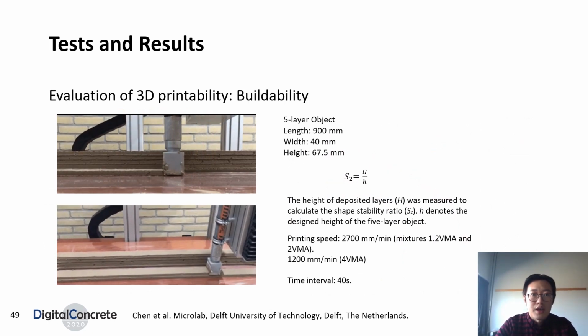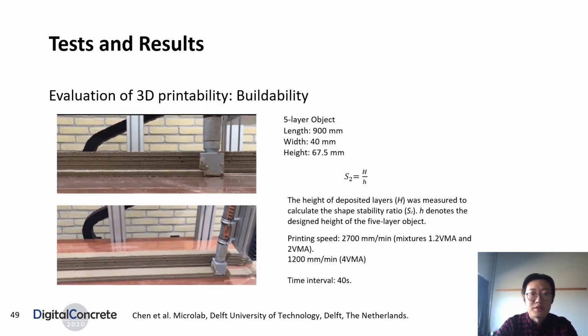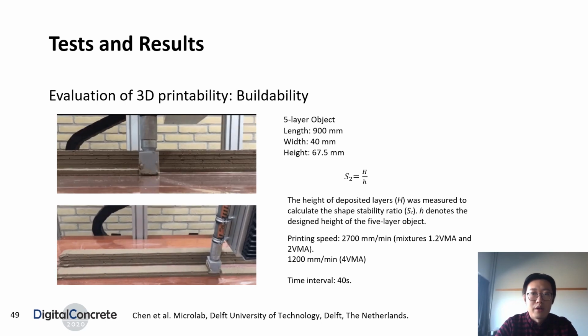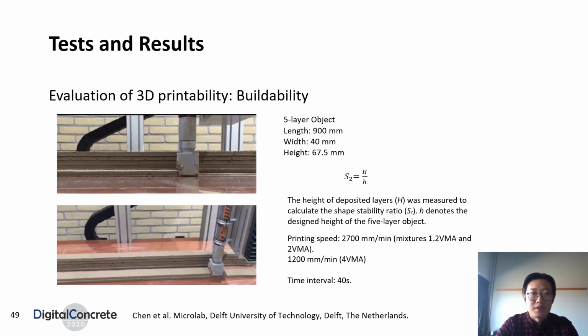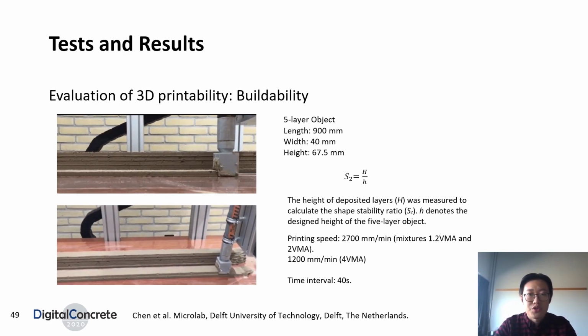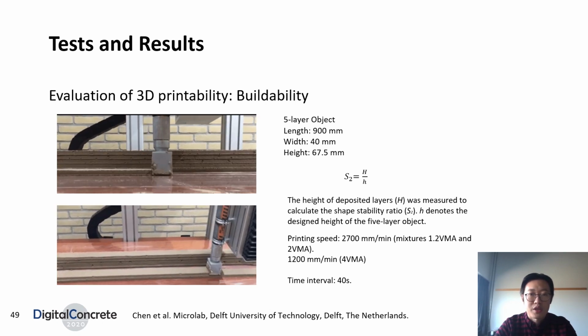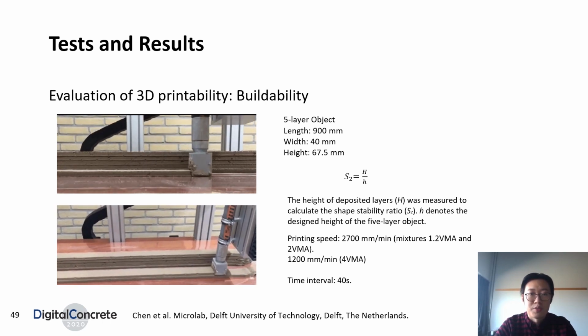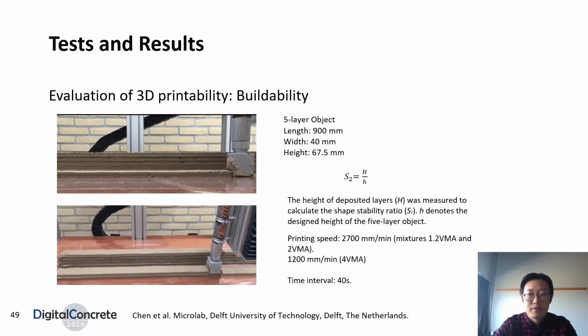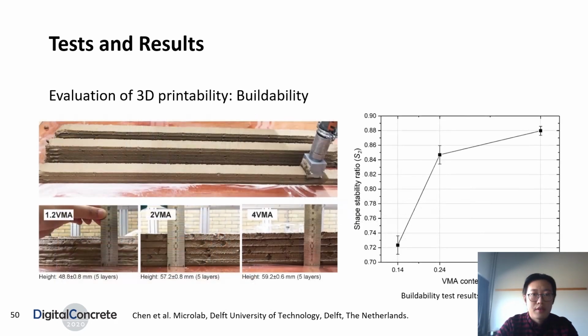The last test about printability is buildability. A 5-layer object was printed by different mixtures. The height of the printed object is measured to assess the shape stability. This test confirmed increasing VMA could enhance the shape stability of fresh mixtures. 2 VMA exhibited close results with 4 VMA.